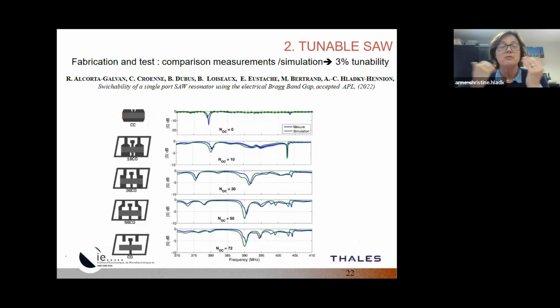Thanks to the previous diagram, we have done fabrication and tests on this device. Here is a comparison of measurement and simulation, and we see 3% tunability. On the left, you have the pictures of the devices. The first is short circuit. The second has 10 electrodes in open circuit, then 30 electrodes, 50 electrodes, and then all are in open circuit, meaning that 72 electrodes are in open circuit. Clearly on this picture, you see the variation of the resonance frequency. It means that you can tune the response of the resonator by a change of the electrical connection. This will be published very soon in APL. It was accepted last week.